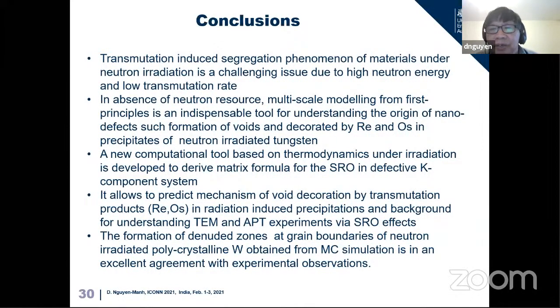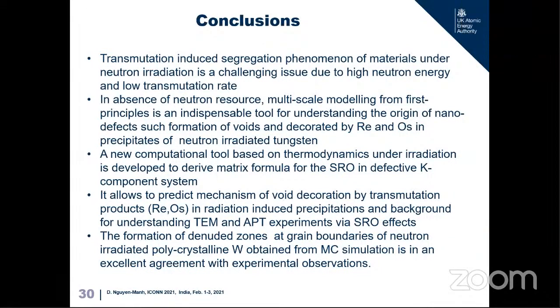I'm not showing it here, but in another work we looked at the effect of oxygen, nitrogen, and carbon at very low concentration, and it appears that even low concentration affects precipitation under irradiation quite strongly. So you're right that oxygen plays a very important role.